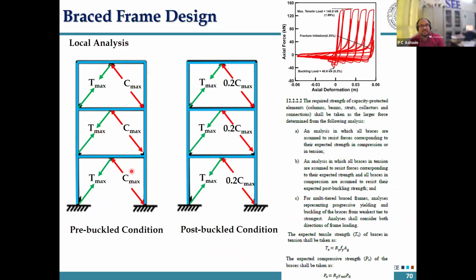The next is I have to check the local also. There's a local analysis in CBF. It's a bit complicated because earlier this was not there. In the previous version of the American code, if you see, it was not there. What it covers here is that there will be an instance in the life of the CBF system where your tension will be maximum and your compression will be maximum initially when the loads are in a certain state. But once the brace buckles, there is only a limited amount of strength that remains in the compression. You remember, once it buckles, there is only a steady value of compression that it can have. It gradually reduces, but the code has limited it to a value of 0.2 Cmax.